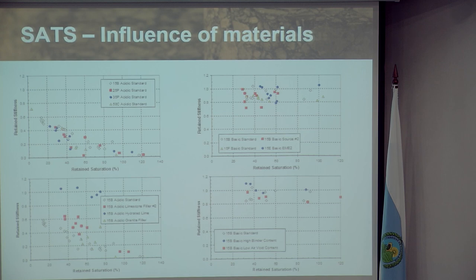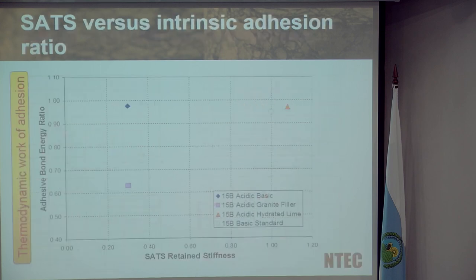And the one on the right-hand side is looking at the volumetrics. We talked a little bit about that in terms of the mixture properties, increasing the binder content to give you a slightly thicker binder film or more coverage of your aggregates, and potentially also playing around with the void content. So this test is extremely useful. How do these results link to what we've done in those previous two sections? Well, the link is actually quite good.